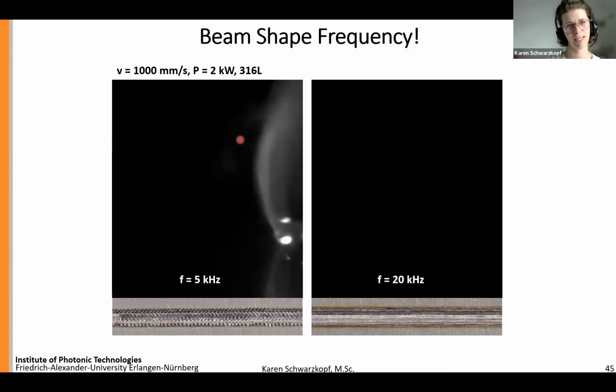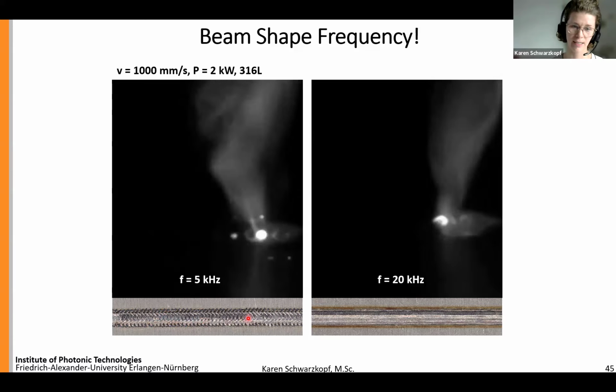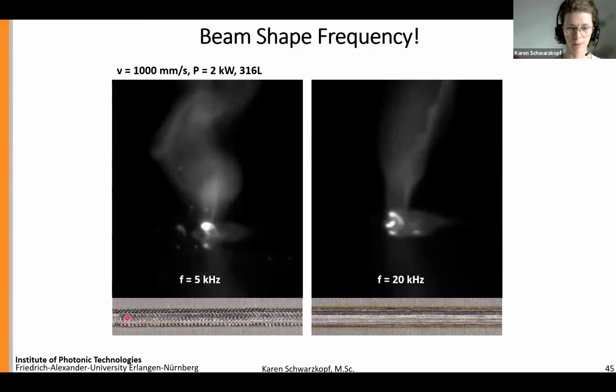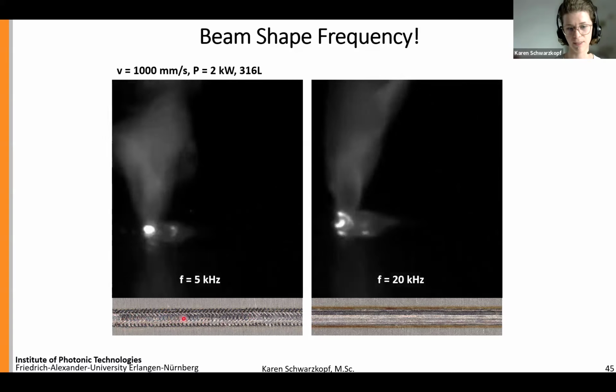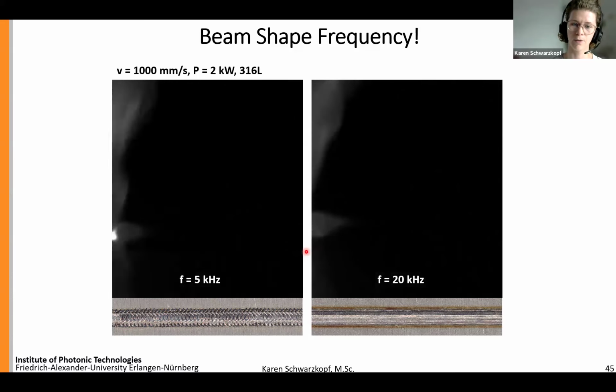Now, I quickly wanted to jump back to the start, where I was referring to the beam shape frequency as a novelty or a unique property of the beam shape technology provided by Civan. As you can see here again, this was the spiral. We can see differences in our weld appearance, which basically shows us that we can steer not only the melt pool shape, but also the solidification of the melt pool. And so a further idea is to really look into how we can use beam shape frequency to steer our process.